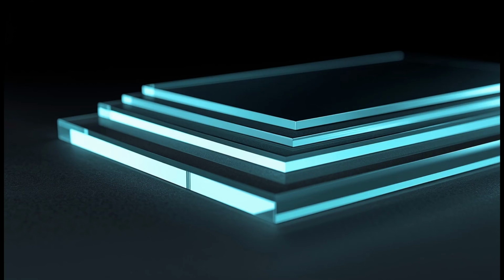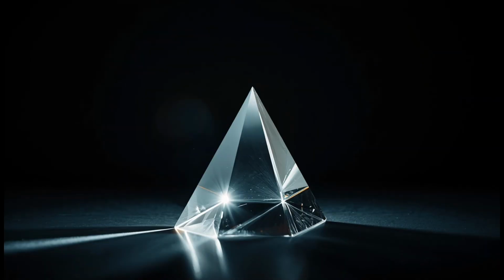The effect can be dramatic. An uncoated glass surface might reflect 4% of incident light. A properly designed anti-reflection coating can reduce this to less than 1%, sometimes to just a few tenths of a percent. In a complex lens system, this means much more light reaches the sensor or film. Much less light bounces around internally, creating artifacts. The result is brighter images, higher contrast, better color saturation, cleaner rendering of bright light sources.